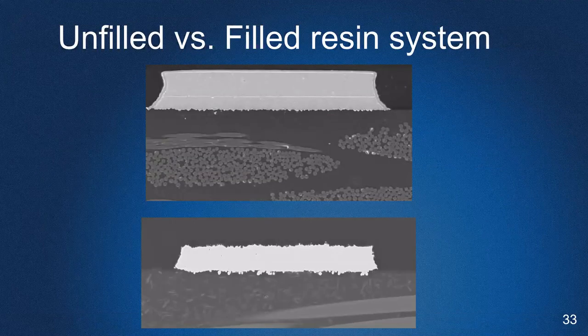There's been some changes in the IPC slash sheets. I don't want to spend a lot of time on this, but again, this is where we can help. There's filled and unfilled systems, and if you look at the lower picture, you can see little tiny flakes of talc. Fillers can be used for changing the electrical properties, but more often than not, they're used for lowering the CTE of the material. More filler can also lower the cost of the material, depending on the filler type and the resin system. So sometimes it's used for cost, sometimes for thermal performance, sometimes for electrical performance, depending on the filler.